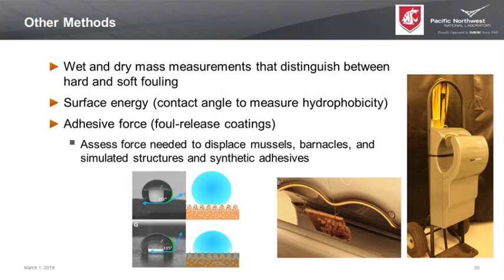We do a lot of contact angle measurements. This allows us to look at the surface energy of a coating, particularly for those foul release coatings and some hydrophobic coatings. So this is a measure of how attractive a surface is to water or to an oil. And we can measure those changes through time as fouling occurs. And then adhesive force measurements, the ability to look at how strongly a mussel or a barnacle sticks to a surface.